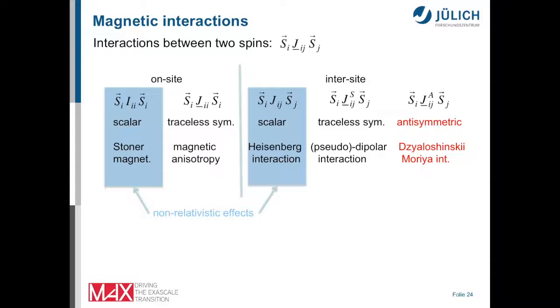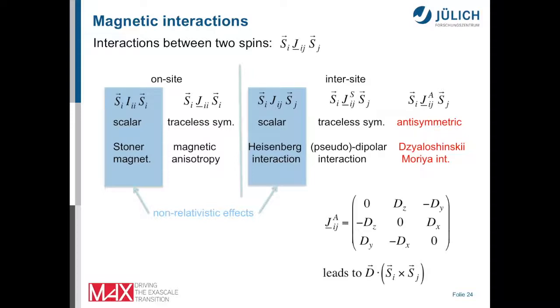And the interside terms, there you have a symmetric and an antisymmetric term. The symmetric one is a kind of dipolar interaction, which is usually rather small, and the antisymmetric part, this is this antisymmetric exchange or Dzyaloshinskii-Moriya interaction, which we will discuss a little bit more in detail.